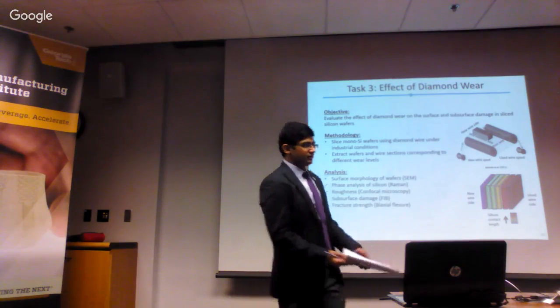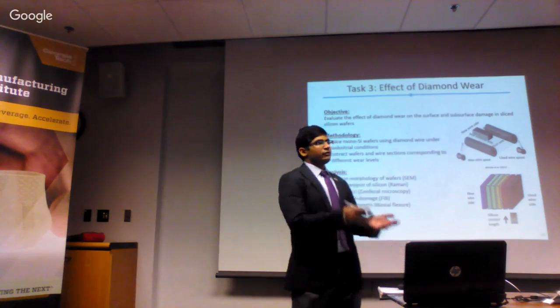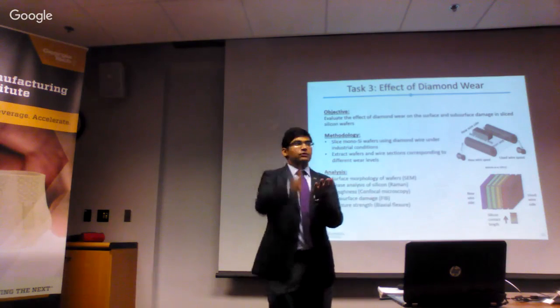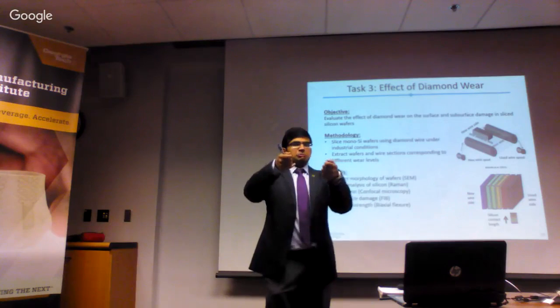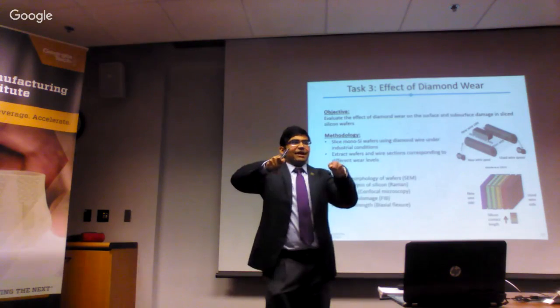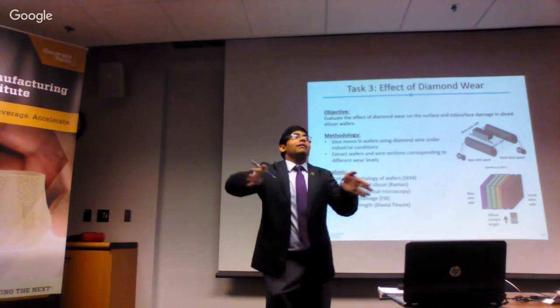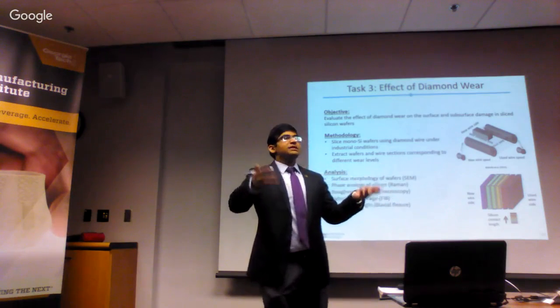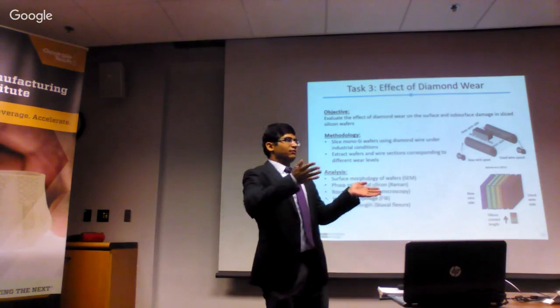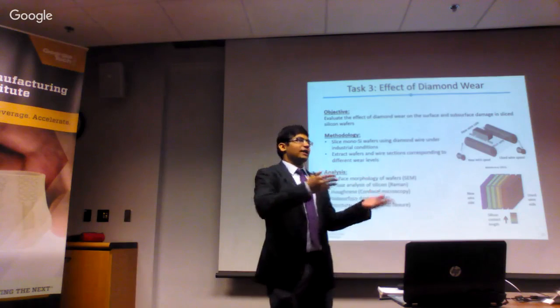So for fracture strength, the median cracks are more important. If you have median cracks, that is perpendicular to the surface. So if you bend a wafer, any crack which is perpendicular to the surface would open up and cause fracture. So median cracks are more important from a fracture perspective compared to lateral cracks.